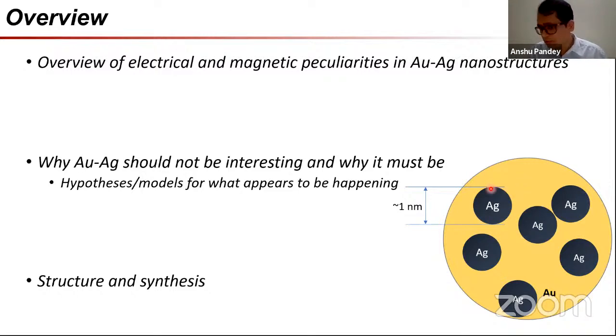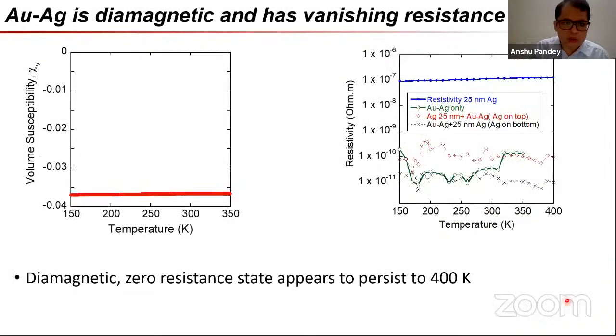So to start this off, let me just start with a simplistic cartoon. Whenever I say AuAg, what I mean is I have silver nanoparticles, these are all roughly 1 nanometer. We are not very critical on the size, but I'll show you the size distribution towards the end of the presentation. In general, these are around a nanometer across, and these are all embedded into a gold matrix. I'll show you what happens if we make errors in the loading levels and so on, but this is the general structure that we'll be talking about and what we mean by AuAg. So, a plurality of silver embedded into gold.